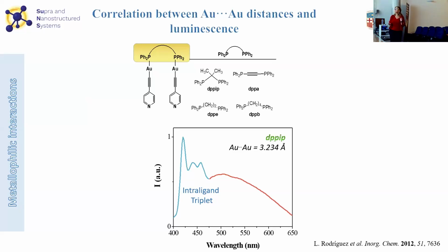And in all cases, what we observe, independently of the distance between the metal centers, is that there are two emission bands. One is a structurally resolved band that has been ascribed to intraligand triplet emission, and another one that is broader in shape that has been ascribed to an excimeric triplet emission.